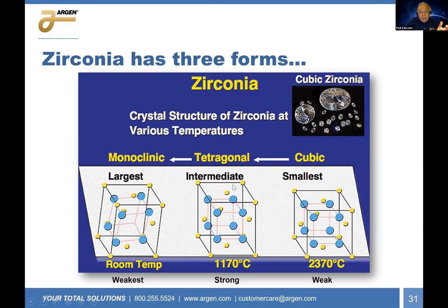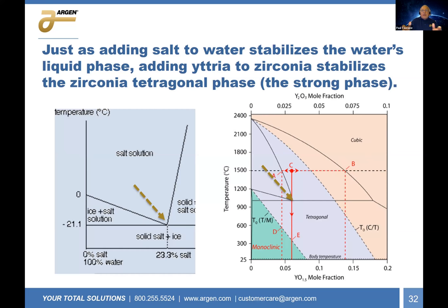Then there's the middle form, the tetragonal form. This is the strong form of zirconia. This is what we want to keep. That's what we want in our dental one. But the material itself wants to go down to this lower temperature monoclinic form. So how do we prevent it from happening? Well, we add yttria to it. And adding yttria to the zirconia stabilizes that mid form, just like adding salt to water will prevent the water from freezing. And the situation is quite analogous.